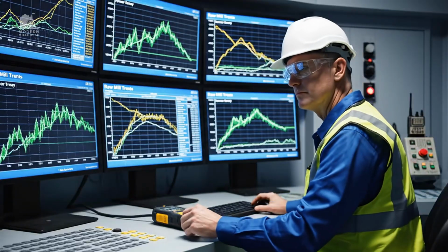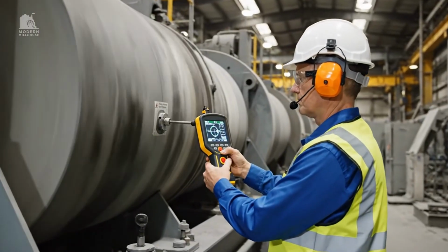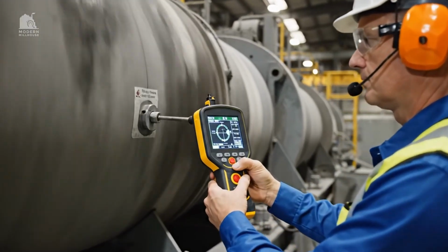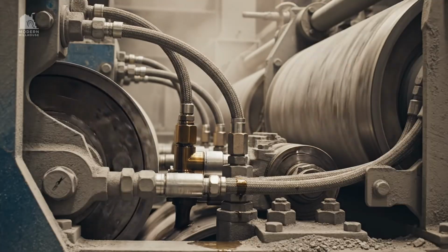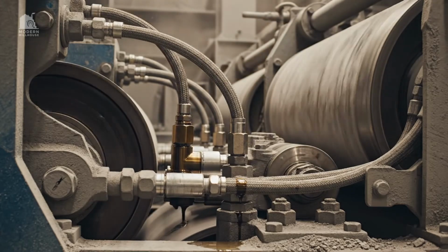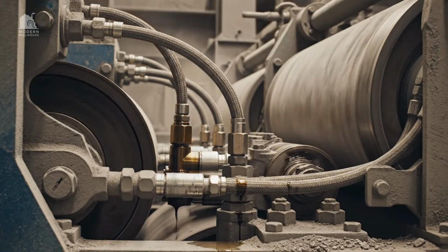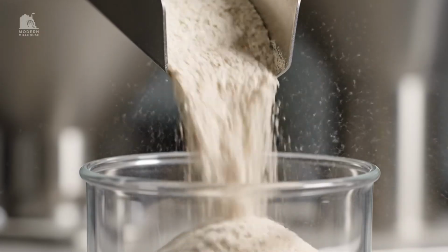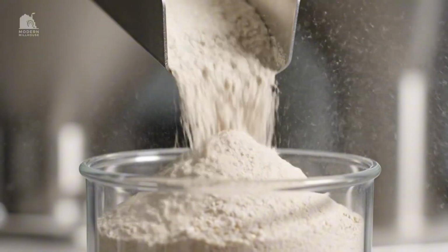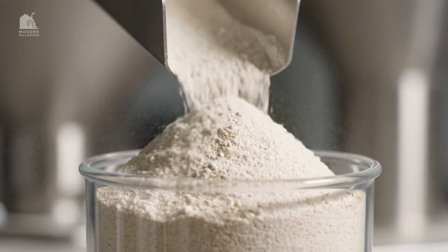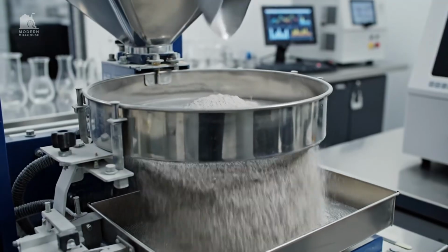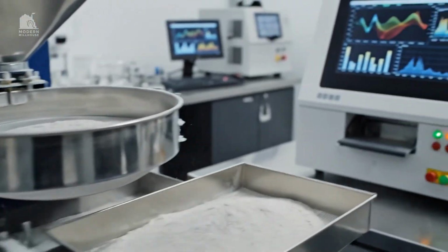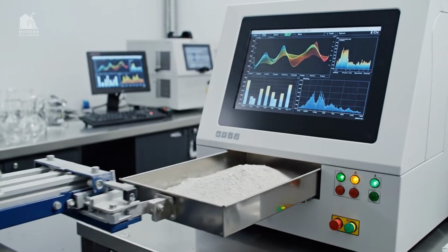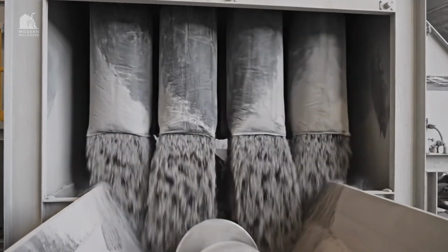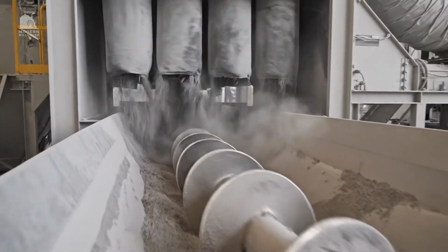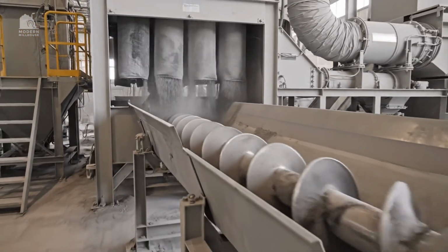Operators monitor vibration and power draw because grinding equipment must stay stable under heavy mechanical loads. Hydraulic pressure maintains roller force, balancing efficient grinding with wear control on abrasive minerals. Raw meal is sampled frequently because the kiln reacts differently to small changes in carbonate and silica balance. Fineness is controlled to ensure predictable heat transfer and reaction rates through the preheater and kiln. Fine dust is captured and recycled, protecting air quality and keeping valuable material inside production.